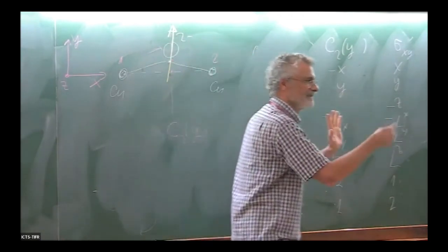It had been shown in J1, J2 spin chains, where you have different first and second neighbor couplings, that you will have a spiral state. It will stabilize a state that is spiral, where this angle is finite, and then it will give rise to a finite ferroelectric moment in those materials. These are the so-called multiferroics, when you have coupling of the spins and different fields, like magnetic field, spins, and electric fields.